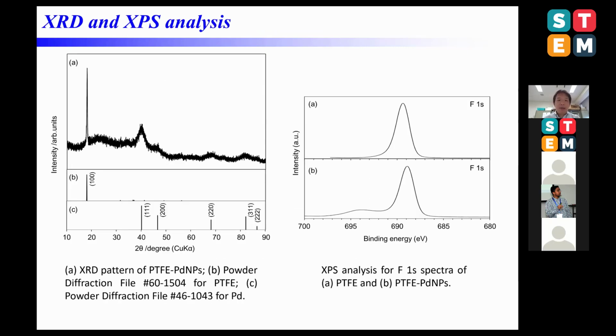An XRD pattern for the black powder is presented here. In addition to the diffraction peak of PTFE, the other diffraction peaks ascribed to palladium were observed. And another broad peak was observed in addition to the peak ascribed to PTFE in the XPS spectrum. Fluorine has more partial positive charge due to coordination to palladium nanoparticles, thereby justifying the shifting of peak position to a higher energy range in PTFE palladium nanoparticles. That is, it's considered that palladium nanoparticles are immobilized on PTFE through interaction with fluorine.